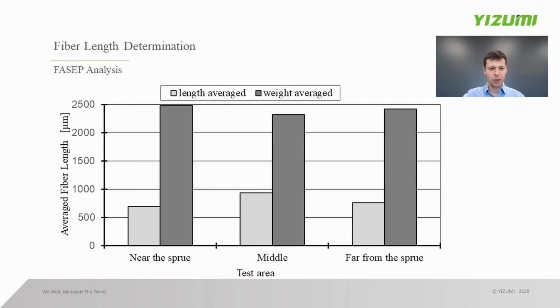And what you can already see here, with a fiber analysis, is the average fiber length for the different parts. One is length averaged, the other one is weight averaged. And you can see there are glass fibers from 500 micrometer up to 2500 micrometer, and the distribution over the part is pretty homogeneous.